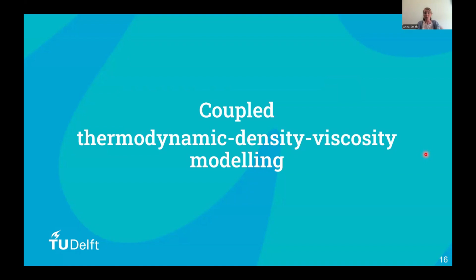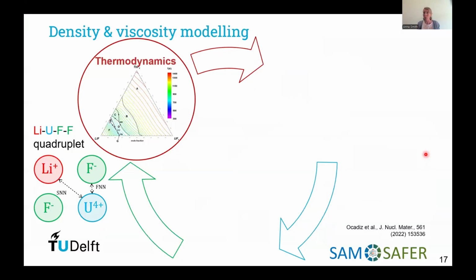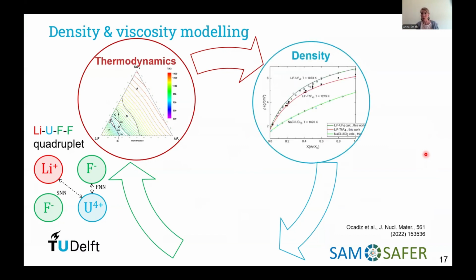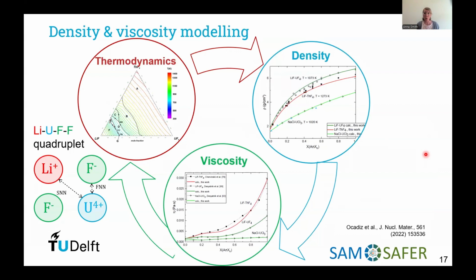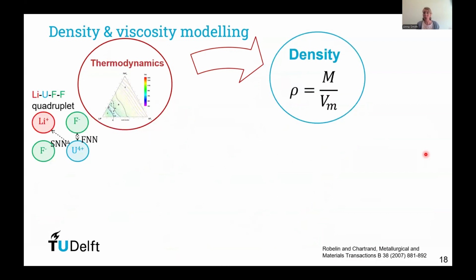And the second one is our effort to build models that couple thermodynamics with density and viscosity, since density and viscosity are also two very important properties for the operation of a molten salt reactor and for the safety assessment. What we would like is to use our thermodynamic models, which use the quasi-chemical formalism in the quadruplet approximation, to build models of the nuclear fuel that can also describe density as well as viscosity in a coupled approach. And here you have an example of our work on binary systems of lithium fluoride with uranium and thorium fluoride, as well as sodium chloride with uranium trichloride. So how do we do that?